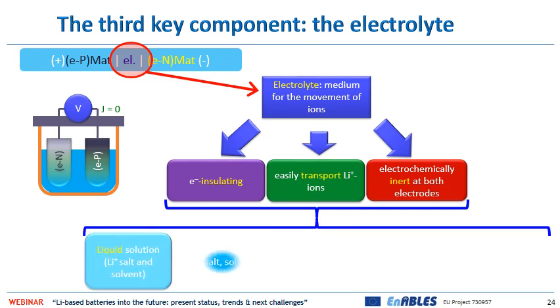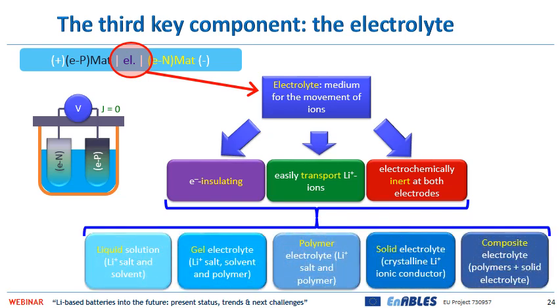We can divide the electrolytes in 5 main classes. Liquid electrolytes, gel polymer electrolytes, in which the liquid electrolyte is immobilized in a polymeric backbone, solid polymer electrolytes, where mainly the lithium salt is directly dissolved in a polymer matrix, inorganic solid electrolytes, such as ceramics and glasses lithium-ion conductors, and finally, the composite polymer electrolytes, which are hybrid materials resulting from the combination between inorganic solid electrolytes and polymers.